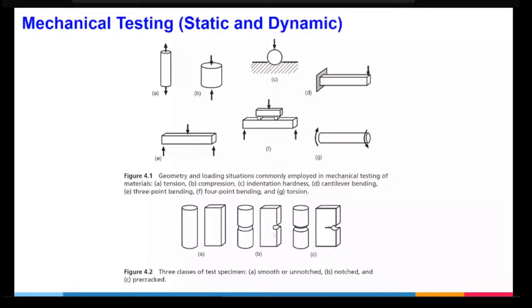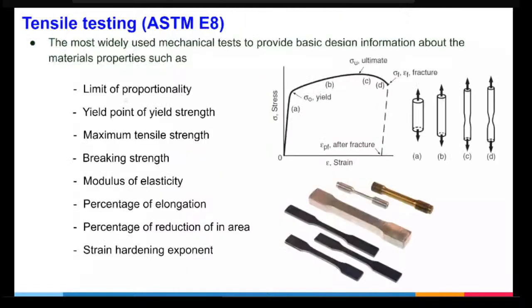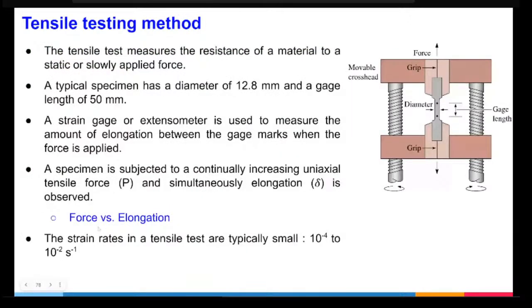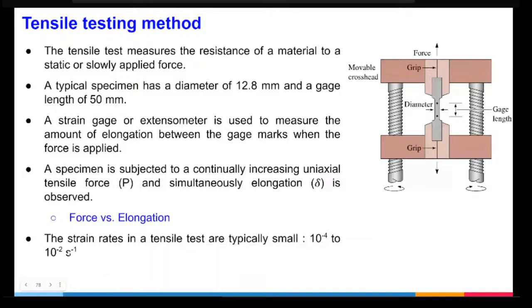It is basically used to find the proportional limit or yield limit, maximum tensile strength, and all other properties. As per ASTM E8, you can make the flat sample, the thicker sample, or cylindrical samples. Once the component is made, you subject it to testing using a UTM machine, and you measure force versus elongation with the strain rate between 10 to the power of -4 to 10 to the power of -2 per second. You make the standard sample and test it using this strain rate, and what you get is engineering stress and engineering strain. From engineering stress and strain, one can convert to true stress and true strain. I'll tell you the advantage of using true stress and true strain in a later slide.